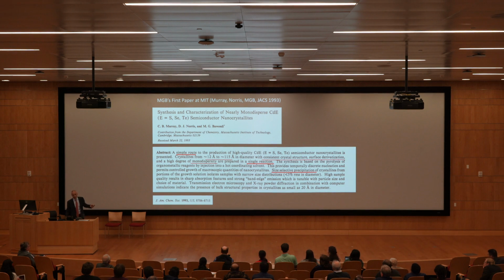And then because we were chemists, we knew we had to purify what we had. And we had this size-selective precipitation, which was a simple way of cleaning the particles, or removing all the side products and unreacted precursors from the solution, so that we can then create what was basically the equivalent of very large molecules in solution that were now the components. So that invention created, so this is 1993, the discovery was 1983, so there's been 10 years between the discovery and the synthesis. Once we had the synthesis, then it became accessible.